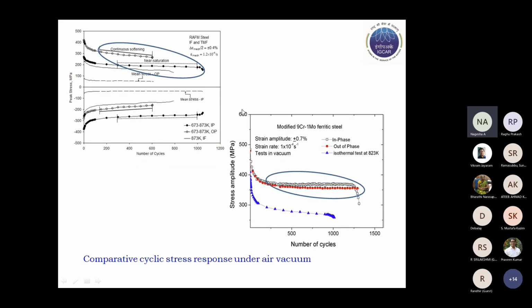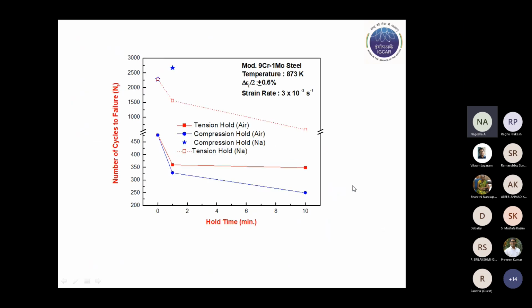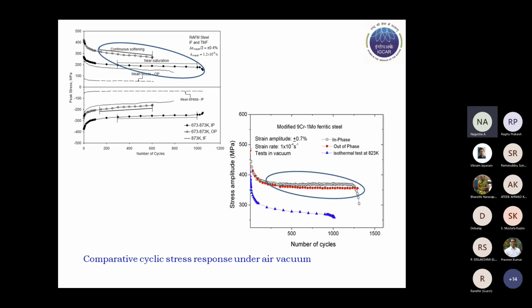Some tests were done in vacuum as well. As you can see, the continuous softening that is happening in air is not there when tests are conducted in vacuum. So this precisely identifies the damage due to oxidation. The lower life under OP TMF, which is seen in air, is not there in the vacuum tests. In vacuum, we saw that OP TMF has a little higher cyclic life compared to the IP case.